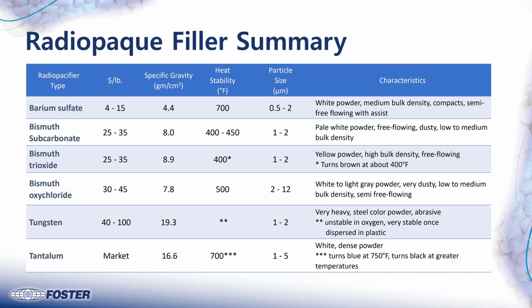So the product line that uses some of the higher performance fillers, we call it Low Pro. We've had that trade name for quite a while now. And these tend to be compounds that are used in neurovascular catheters and cardiovascular catheters. We have another product called Low Pro Clear, and it's with a radiopaque filler that matches the refractive index of the polymer that it goes in. We're very limited to the polymers because there's only so many polymers that do match the refractive index. So that's how you get it optically transparent.